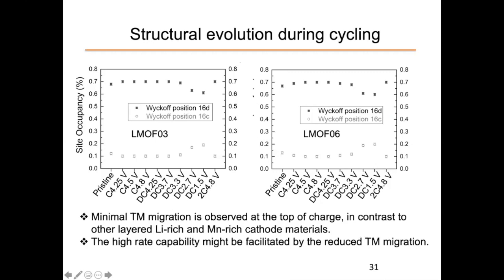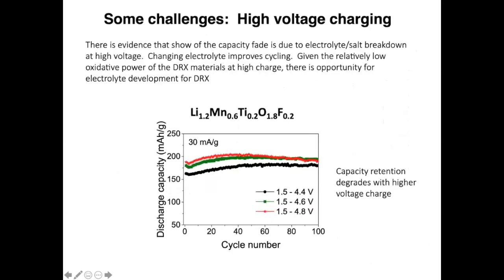Here's the site refinement on the different positions. At the end of discharge, there's a little bit of change, but we're actually not convinced yet that that's real, but that it may be part of the refinement. So the materials seem to be intrinsically relatively stable against cation migrations.